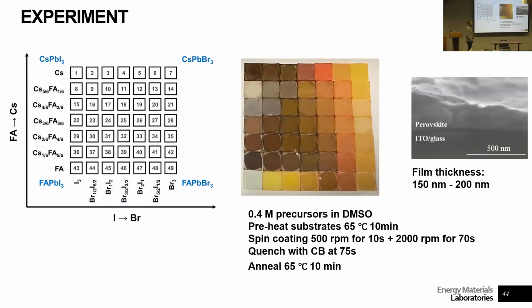So iodine is the front runner for stability right now? Yeah. Because what happens is if you start mixing with bromine, or mixtures of bromine and iodine, the bromine segregates and the iodine segregates. Then you have multiple peaks, kind of like what I was showing. You have several emission peaks, and that means that you have heterogeneity. So we want to keep it in the pure iodine regime. And that also gives you the most narrow bandgap.